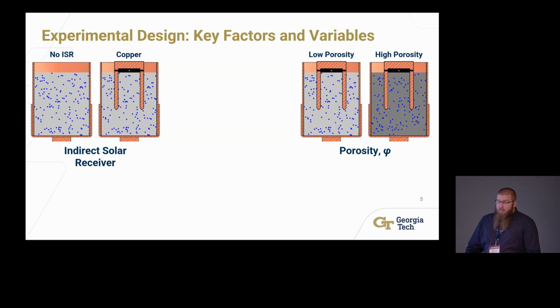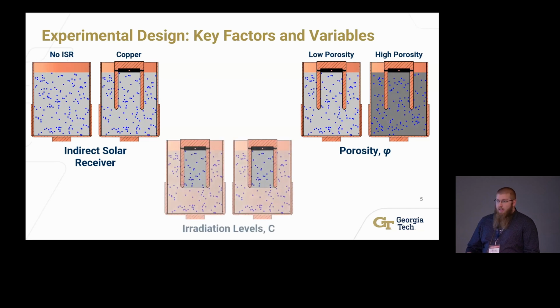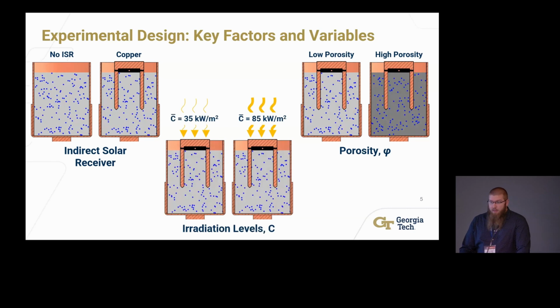what the porosity is of these systems. So we have two different levels, the limits of which we could do in this experiment. The lower limit is where, if you go lower, the indirect solar receiver doesn't stay in place; any higher and I can't press it in. And the final factor is the irradiation levels at two different values, 35 suns and 85 suns on average, to see how much of an impact that has on the sublimation rates.